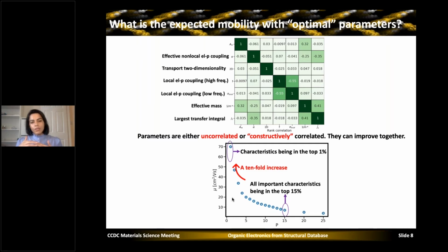The point is that for the majority of these parameters, the 5 parameters that are listed in the previous slide, there are some general design strategies in the literature. The only one which remains without any general design strategy is the dynamic disorder. Because as I said earlier, the calculation of these parameters has been really challenging, and if the number of studied structures is so limited, the structure property analysis does not make sense. So at this point, we had a unique large set of computed dynamic disorder values, a library composed of 5,000 entries. This was an excellent opportunity to go into the detail and figure out the materials characteristics of those showing a smaller level of dynamic disorder, and how we can design such structures.